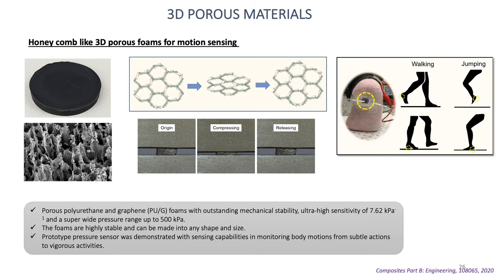We combined molecular assembly with ordered arrays of structures such as honeycomb-like features in graphene foam. We made a nanocomposite foam by combining polyurethane with graphene — the addition of graphene leads to formation of honeycomb-like structures, and the porous foam exhibited excellent strain-sensing properties. We also demonstrated motion-sensing properties such as finger bending, walking, and jumping, rendering application in various areas for pressure sensing.